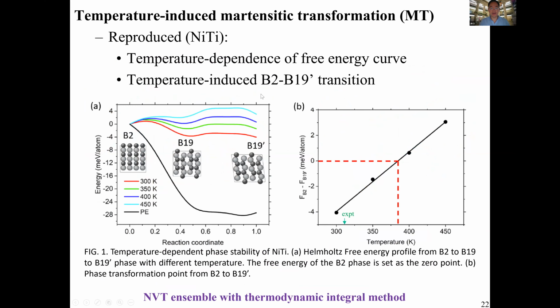And so what we have done is a potential mean force calculation to get the finite temperature free energy. So at 0 temperature, B2 is phonon unstable. So actually B19 prime is the locally stable, actually globally stable phase. But as we raise the temperature along the reaction coordinate, we compute the average stress, which is the generalized force in this phase transformation, and we integrate this thermally averaged force. And so at some temperature, which is about 380 Kelvin, we reach the first order phase transformation, and then B2